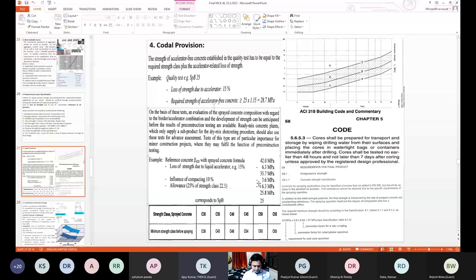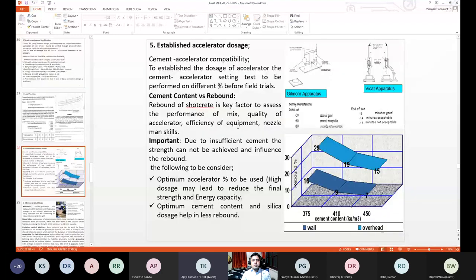Now I am on established accelerator doses. While we are designing the shotcrete in the lab and making the mix, we should keep in mind that the accelerator should be used in appropriate doses. If the accelerator is more than the recommended dose, your strength will be higher and your shotcrete operation will be okay, but the shotcrete will be in a burning stage, and later on your strength will not be achieved in situ. So you have to establish this through the Vicat apparatus or Gilmore apparatus. The recommended setting time for shotcrete is a maximum of 4 minutes, which is desirable and acceptable.